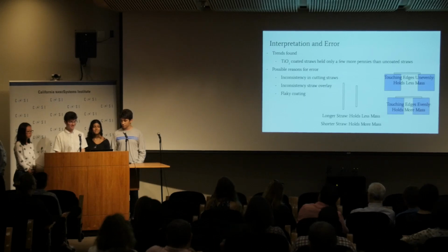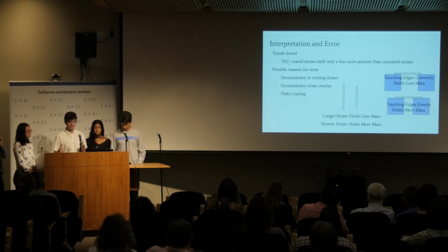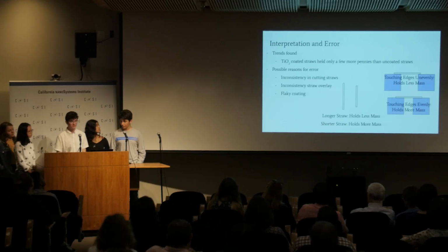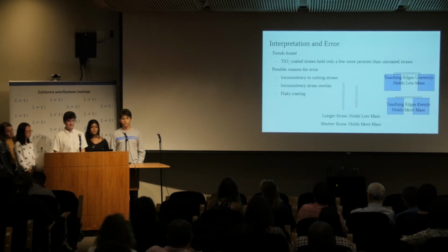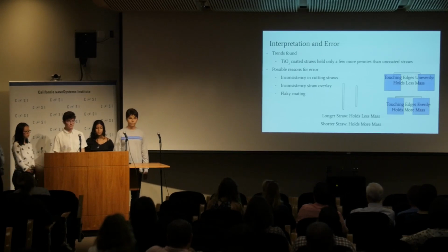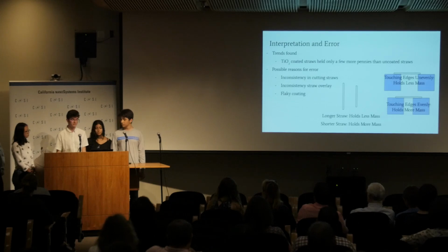And inconsistent straw overlay, so if it's unevenly placed, then it would hold less weight, but if it's evenly placed, then the weight distribution would have been better and it would hold more weight. And then the last thing that could have affected our results is that titanium dioxide by nature is really flaky. It's what's in white paint, so when it flakes, it makes micro cracks, and it takes away the nano features, which would make it more hydrophilic than hydrophobic, which would skew our results.